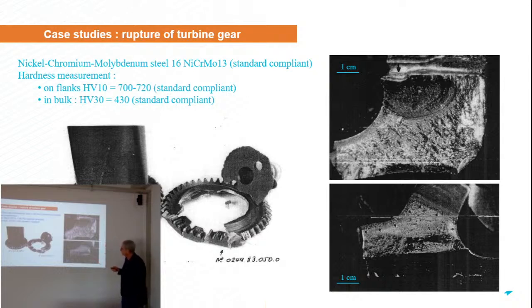And in bulk, we get 430, which is also okay in terms of standard compliance. The material is harder at the surface than in the bulk because it is a turbine gear, and it must be very hard at the surface due to the mode of loading, the contact between the two parts.